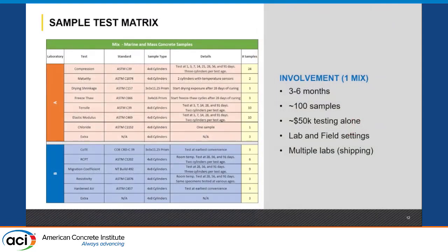This is what the test matrix typically looks like when we do these marine concrete mixes that need a 100-year service life. One mix can take 3 to 6 months to qualify. It's about 100 samples, beams, cubes, well, not really cubes, but cylinders, beams. It's about $50,000+ of testing.